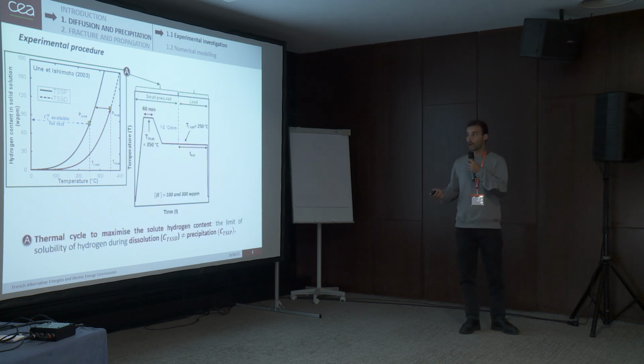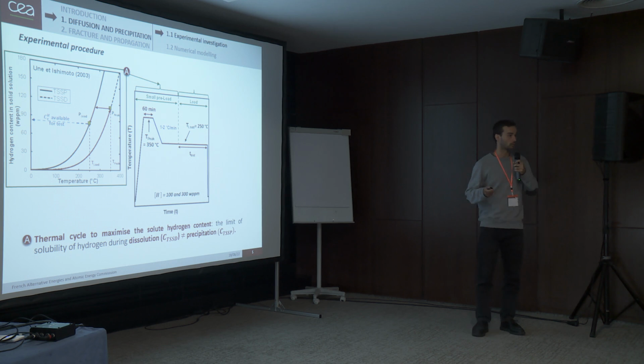So during our tests, we want to apply 250 degrees. At room temperature, there is no hydrogen in solid solution. So to be nearest to the terminal solubility in precipitation, we have to heat up to 350 degrees, then cool slowly to 250 degrees. So this is the first step of our experimental procedure.